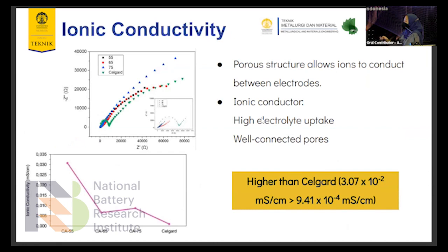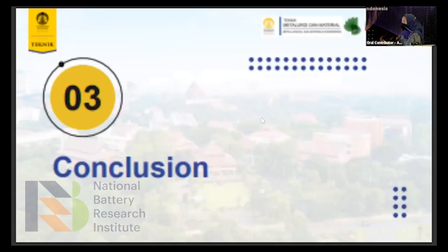And the last thing we observe is the ionic conductivity. This ionic conductivity is contributed by the porous structure that allows ions to conduct between the electrodes. This is also related to the high electrolyte uptake and well-connected pores that we have seen in the SEM image. From this research, we have concluded that the produced membrane has higher ionic conductivity than the Celgard or the commercial separator.